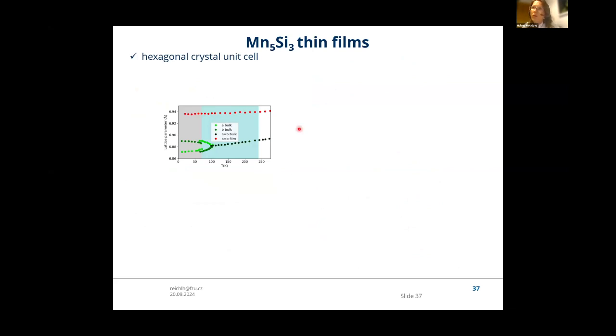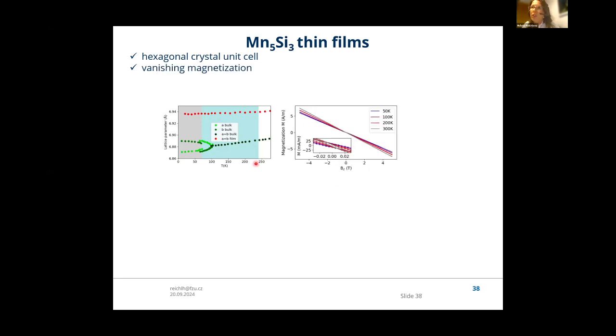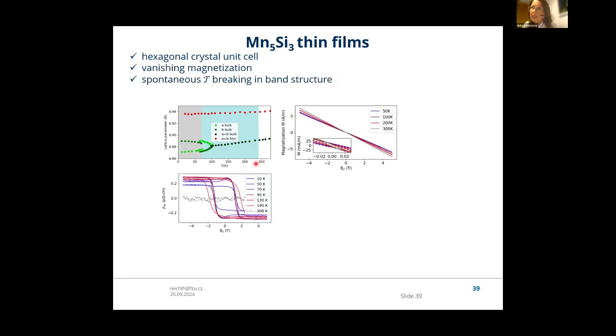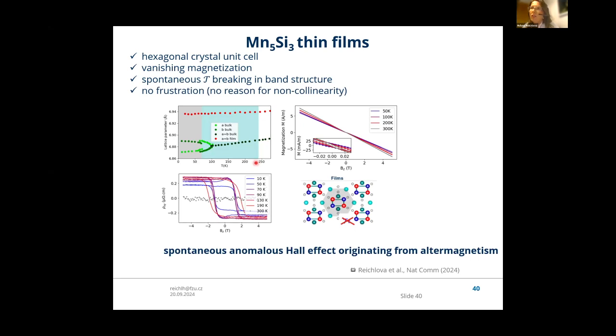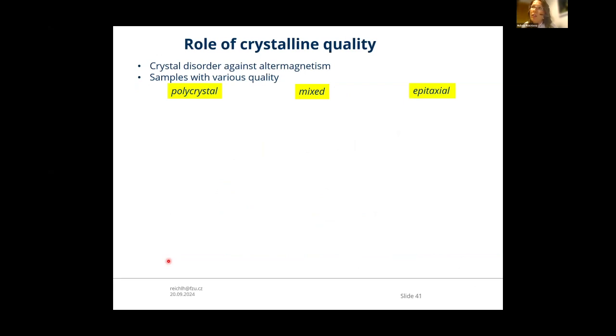So just to summarize, we checked the hexagonal unit cell, we checked the vanishing magnetization, we checked that the anomalous Hall effect provides evidence of the spontaneous time-reversal symmetry breaking, and we have this confirmed theoretically, that this crystal structure and magnetic structure allows for altermagnetism. Therefore, it's strong evidence that the spontaneous anomalous Hall effect in that case originates from altermagnetism. As I mentioned, it's not a direct proof. So there are also some additional hints why we think that it's indeed of altermagnetic origin.